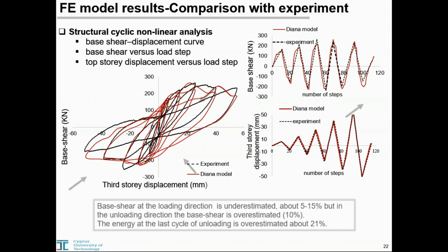A discrepancy appears in the last cycle of loading, as you can see here. The shear force capacity and energy, the energy is calculated as the area enclosed on the loop in the base shear versus displacement diagram, are overestimated compared to the experimental results. This may be attributed to high nonlinearities that are introduced at that stage during the experiment. Based on the result, the base shear of the loading direction is underestimated about 5%, but in the other loading direction, the base shear is overestimated 10% at the fourth cycle of loading. The energy at the last cycle of loading, as you can see, is overestimated about 20%.